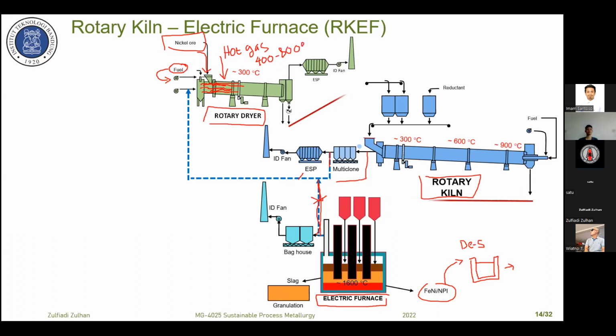This huge amount of hot gas contacts directly with the wet nickel ore. During the movement of the ore and its contact with the hot gas, the moisture is released and removed. At the end, the moisture, H2O, goes to the off gas together with dust, and the product, what we call conditioned ore or dry ore, has a water content of around 20%, and this is sent to the rotary kiln, where it is charged together with reductant.